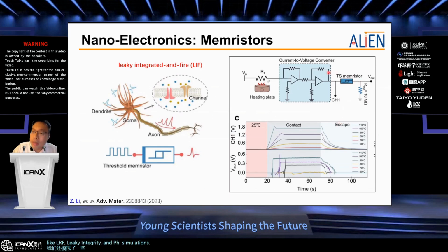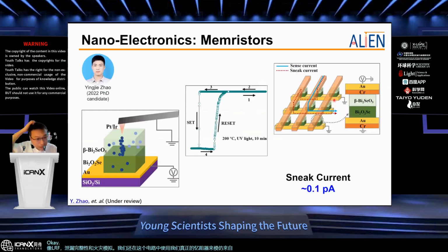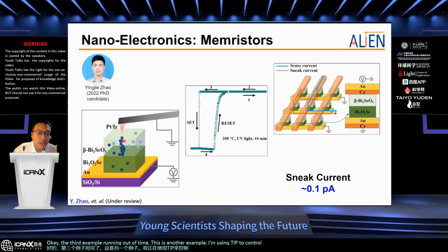And we also use our real memristor in this circuit to mimic the heating responses from the memristors. Okay, the third example, really running out of time. This is another example, using the tip to control the oxygen vacancies and also control the filaments. So the advantage or innovation in this work is we have a further interface between the top and bottom. Here we can have not only memristive behaviors but also rectifying behavior, so that this can greatly reduce the sneak current from the adjacent cells when this cell is working, and the adjacent cell may have sneak current if this is not rectifying.